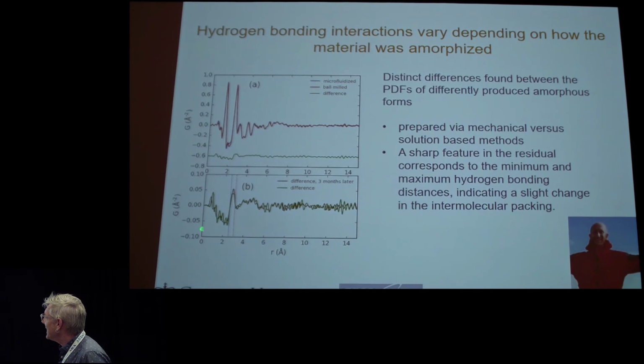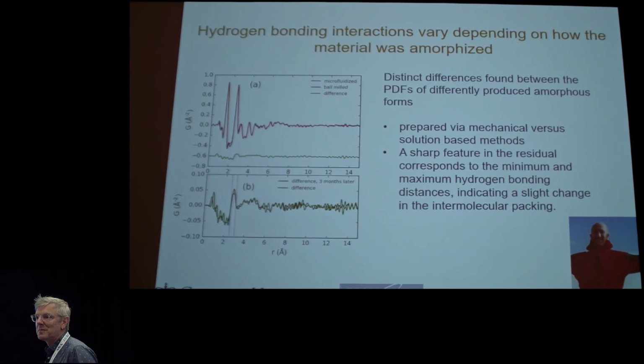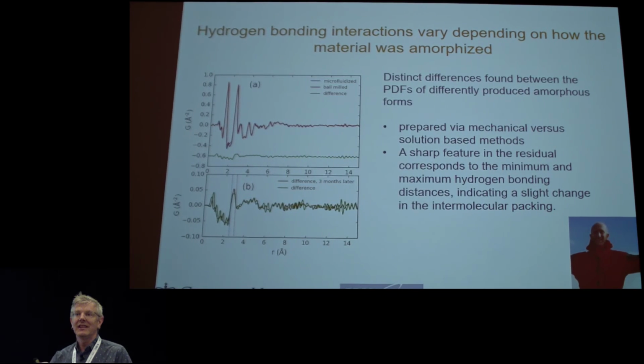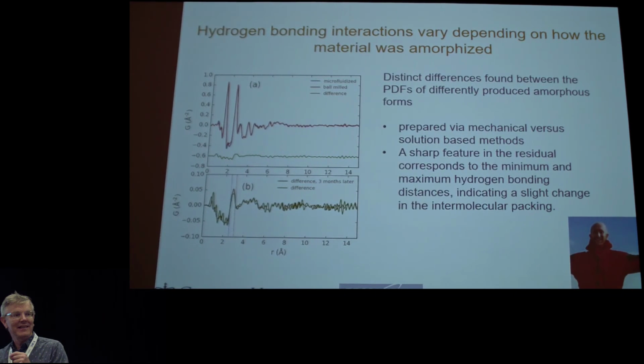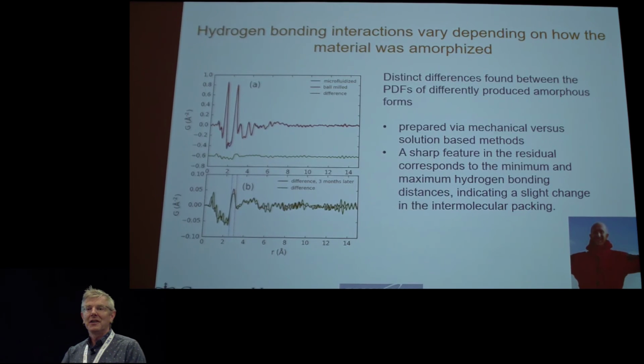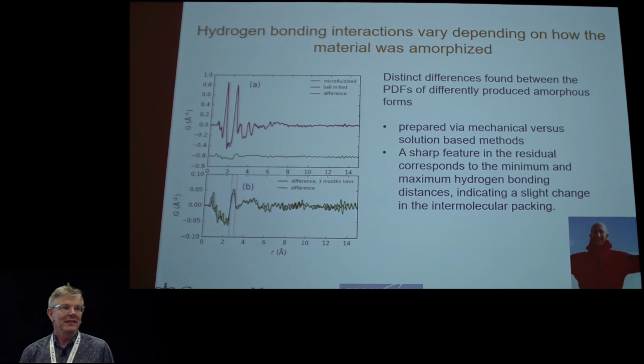And this peak here is actually a hydrogen bond peak. It's the oxygen to nitrogen distance in the hydrogen bond. And so we're pretty amazed about this. We can actually show that there's a slightly modified hydrogen bonding network between these two amorphization methods.